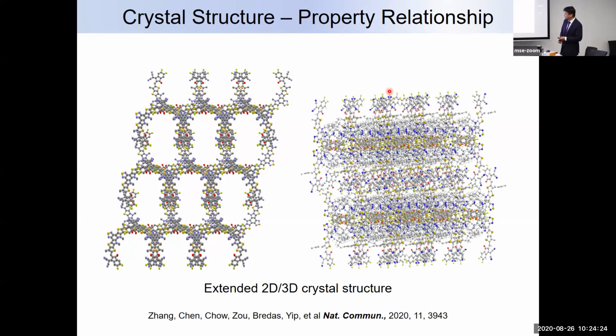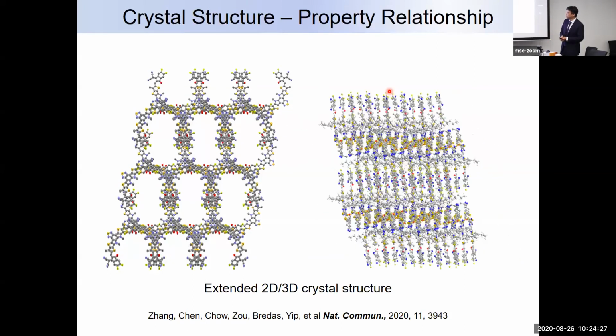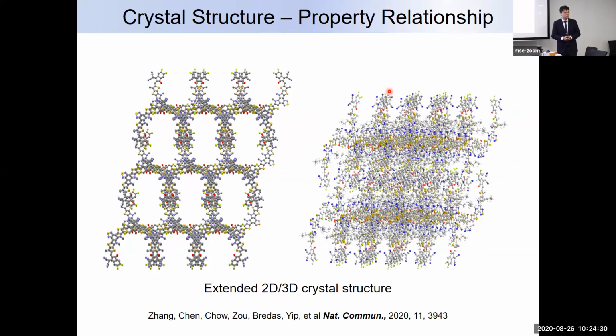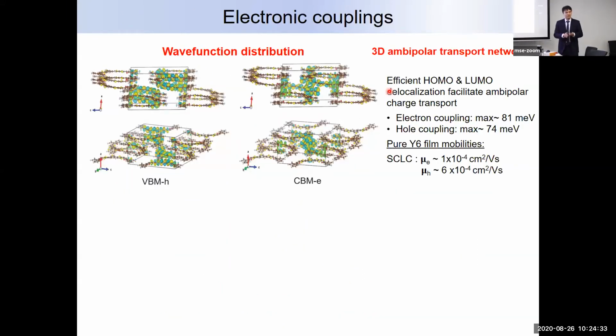And therefore, with this crystal structure, we can start to use a DFT calculation, trying to understand the electron and also hole transport pathway within this crystal. The one on the left here corresponds to the valence band, or the HOMO level delocalization. And you can see that this HOMO delocalization is actually pretty good. It is three-dimensional, right? It's spread in the lateral way and also in the vertical direction. So unexpected, right? They may also have hole transporting properties, although we are using it as an acceptor for electron transport.